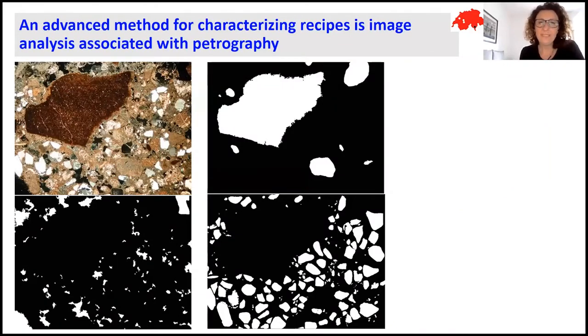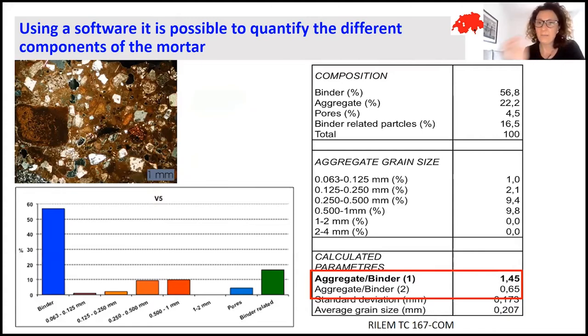To study the texture of the mortar, for example, the percentage between the aggregate, the binder, the porosity, the shape of the porosity, and also the presence of binder-related particles, it is possible to associate the petrographic image with image analysis. Through particular software and algorithms, it's possible to quantify and obtain textural graphs concerning the different mortars, and have parameters such as the distribution of the aggregate, the binder-aggregate ratio, the quantity of porosity, and so on.